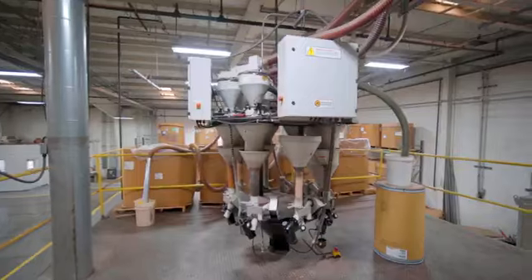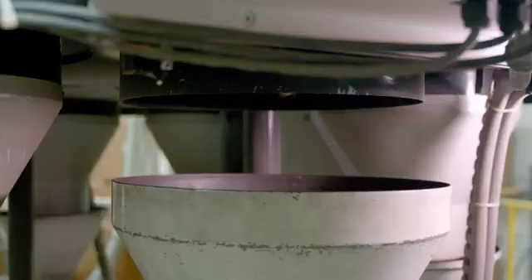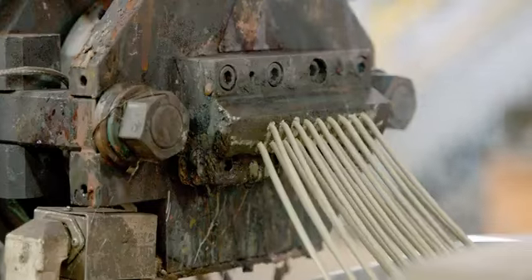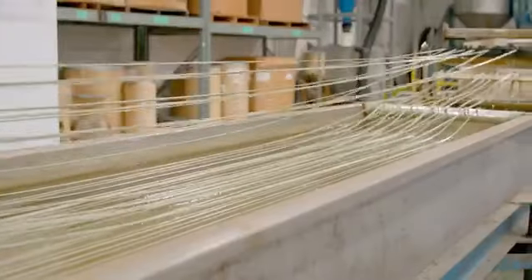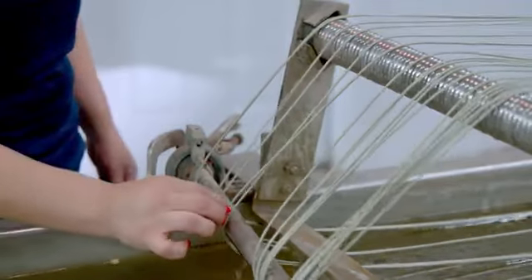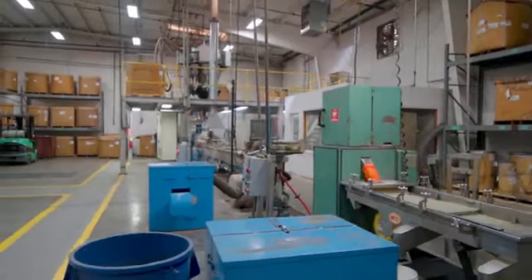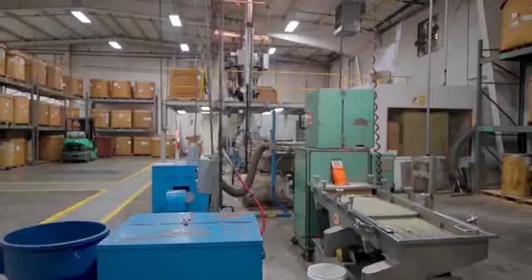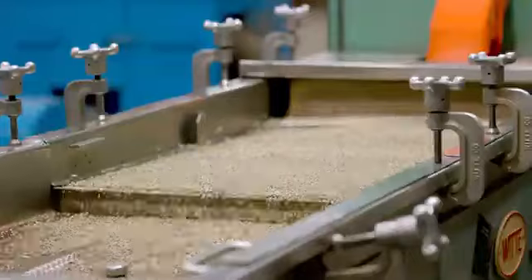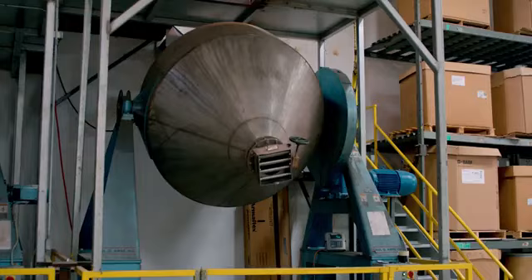This process takes the different monocolor polypropylene or nylon pellets and melts them down to a semi-liquefied state. They are then pressed through the multi-hole die head into a cold water bath, which transforms the melts into solid, continuous spaghetti strings. Next, the strings move to the cutter that breaks the strings down to pellet form, are sorted out using the shaker, and finally, for a consistent and uniform size pellet, go into the rotary mixer while adding a non-static material to avoid static charges.